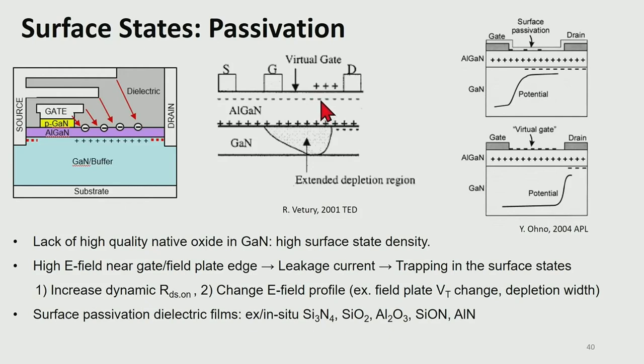So first, the electron trapping mechanism is leakage current induced surface trapping. In GaN devices, high voltage blocking is done by multiple field plates. This means that these field plates are exposed to the high electric field. So electrons in the field plate can be ejected due to this high electric field, and they can be trapped in the dielectric or dielectric-GaN interface. Especially the GaN surface has many donor states where the electrons can be trapped.